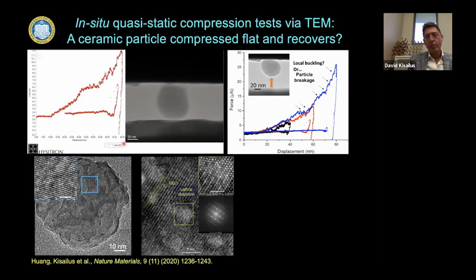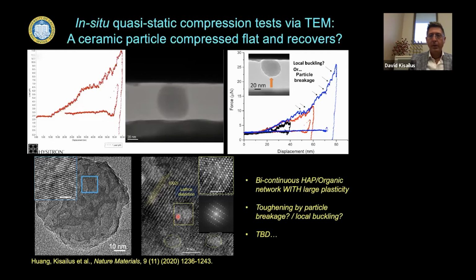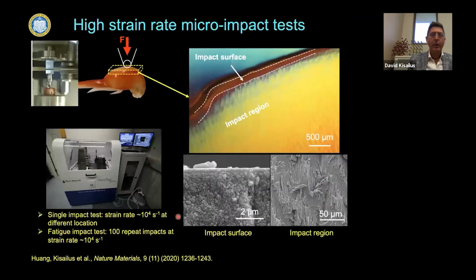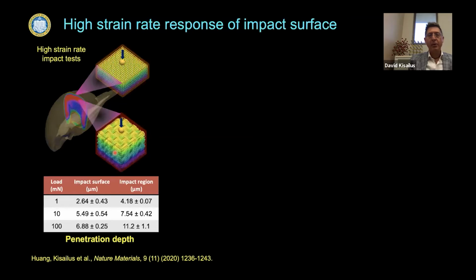And so this is a little bit more information showing this bicontinuous particle that's found in the impact surface. And again, you can actually see some lattice distortion due to the organic that's occluded within the mineral. And so the question is, okay, this is interesting under quasi-static conditions, but what happens under high strain rate? So we have taken the club and mounted it and performed some high strain rate impact testing in this micromaterials device that we have in my lab, and impacted on both the surface as well as the underlying impact region.